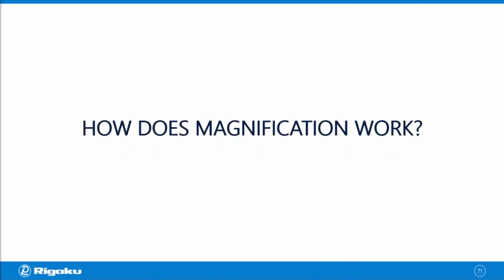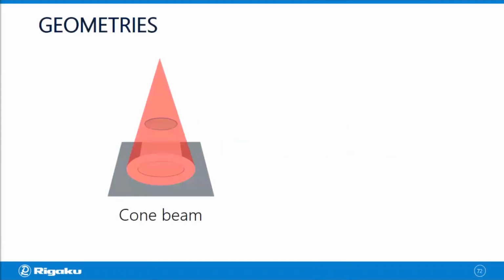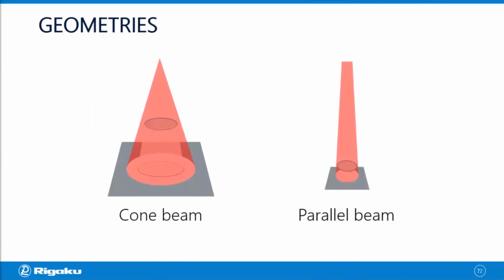And how does that magnification work? So that depends on the geometry you're using. And the cone beam geometry, which has X-ray source here, detector and the sample, and you have a cone-shaped X-ray beam. This is one of the most commonly used X-ray CT geometry for commercially available CT scanners. And the other geometry is called the parallel beam geometry. Again, you have the X-ray source, detector, and the sample.